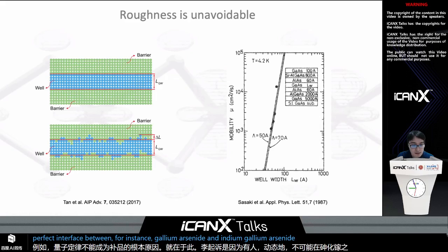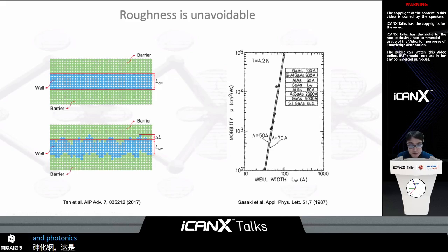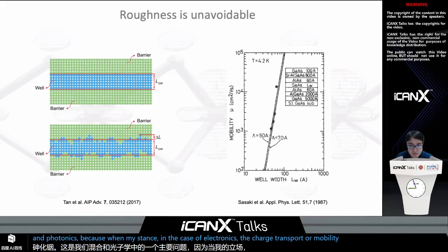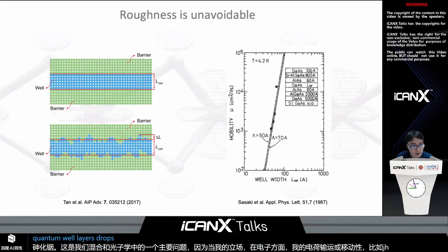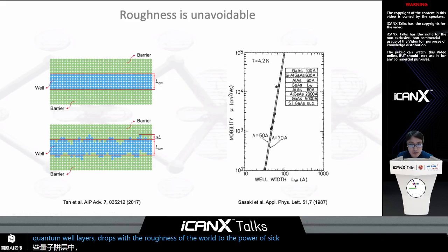And this is a major problem in both electronics and photonics, because, for instance, in the case of electronics, the charge transport or mobility of the electron gas living in these quantum well layers drops with the roughness of the well to the power of 6. So the charge transport is extremely sensitive to the roughness.